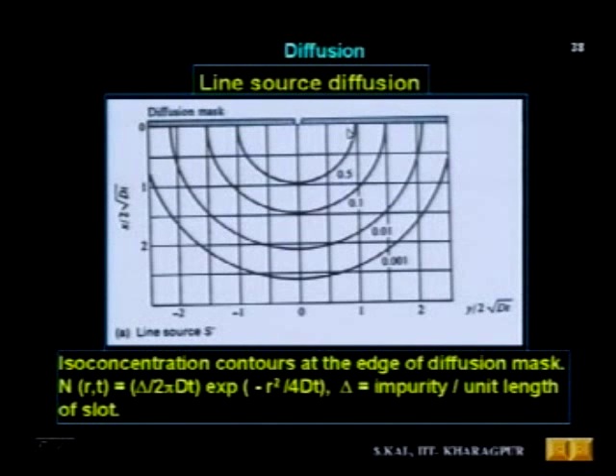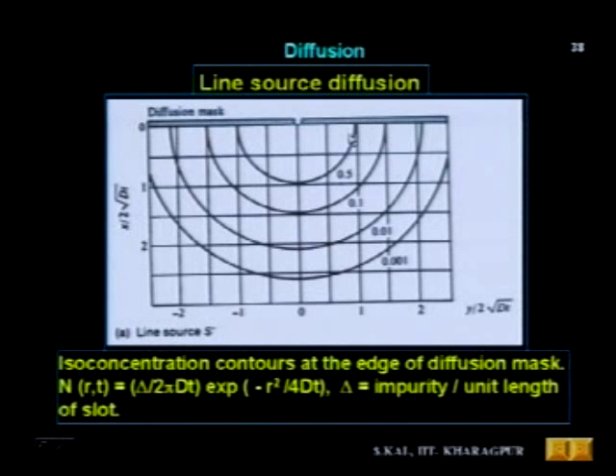Iso concentration contours means everywhere it is 0.5, and what is this value? This is the C2. C2 is n divided by n surface, the concentration at that point divided by n surface. That is 0.5. That means whatever the surface concentration is, half of it is here. So along this line you will get half the concentration of the surface. Similarly, along this line you will get 0.1, 1/10 of the surface concentration, at this contour. And this doping profile is given by n(r,t) equal to delta by 2 pi dt e to the power minus r square by 4 dt, where delta is the impurity per unit length of the slot. This is the slot. Okay, that is the doping profile for line source diffusion.